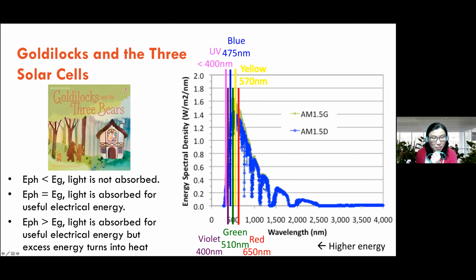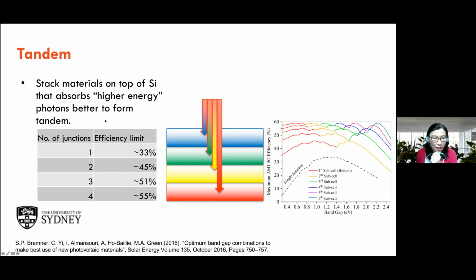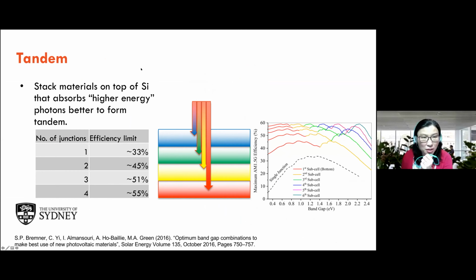So you can see that there are some solar cells, for example, silicon. Most of the time for silicon, the photon energy is higher than the band gap, and therefore you have a lot of waste heat. So the idea of tandem is to stack the materials with different band gaps so that each of them does its job properly. So you have a Goldilocks that can sleep in a big bed, a Goldilocks that can sleep in a middle-sized bed, and a Goldilocks that can sleep in the smaller sized bed.